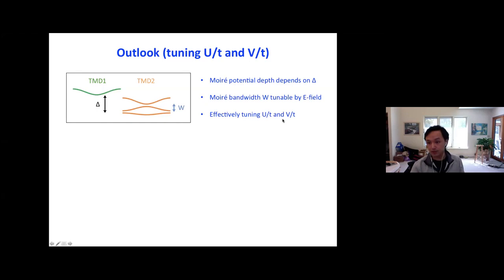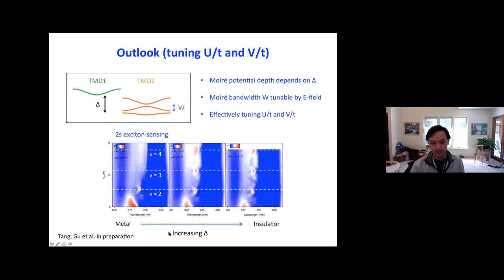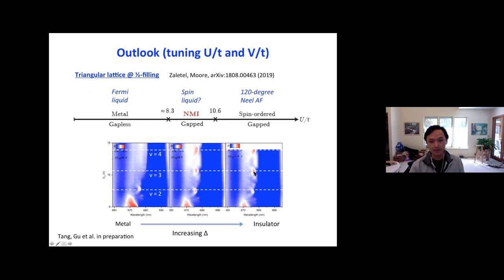And this is some preliminary data. From this side, we increase delta from a smaller value, and you can see that the Mott state, which is not there at the beginning, emerges after you decrease the bandwidth of the system. So this is really close to something like a Mott-Hubbard transition, that is a metal-insulator transition induced by tuning U over T in the system. We think it is probably quite interesting because it's a triangular lattice as well. So maybe at some critical U over T, if we can also measure the magnetic response, this may be a quantum spin liquid state near some critical values of U over T.